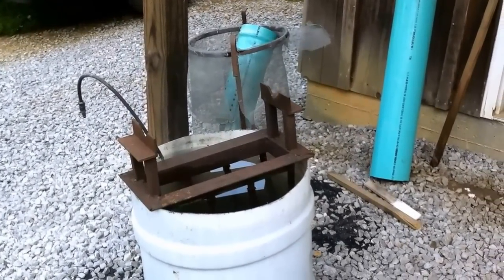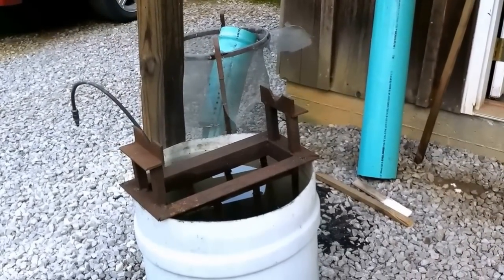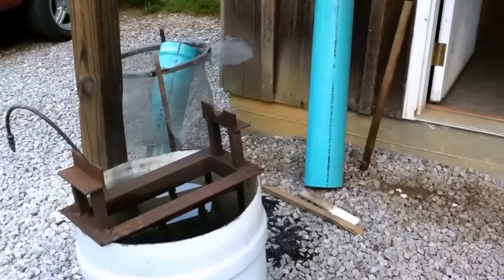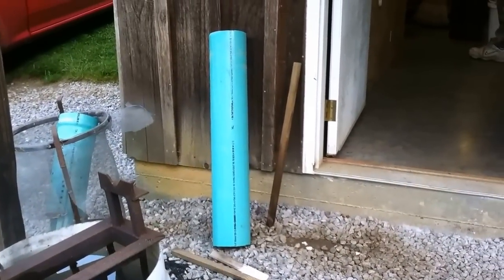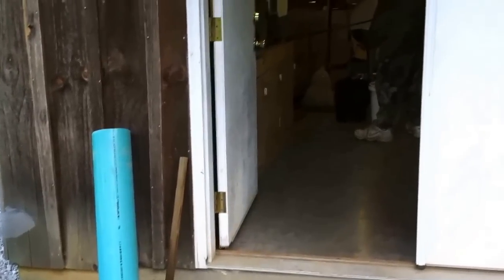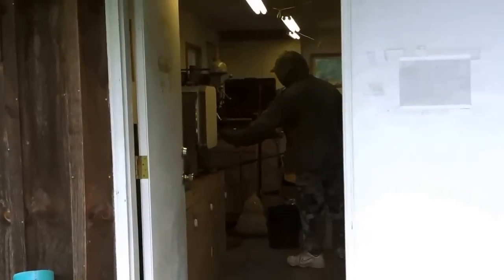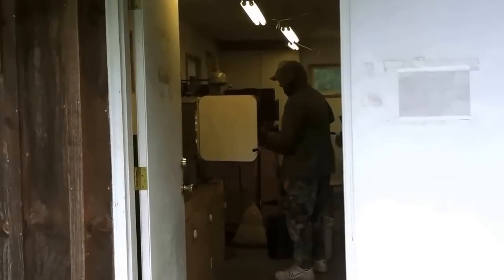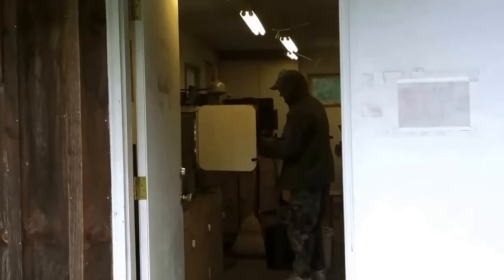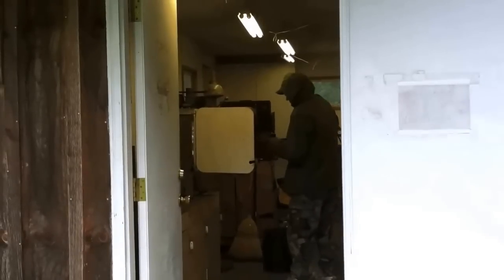Okay, we've chilled our quench water down with some ice, got it down around 55 degrees, and our program is complete. We're getting ready to pull the pack out of the oven right now. Go through this quench process.